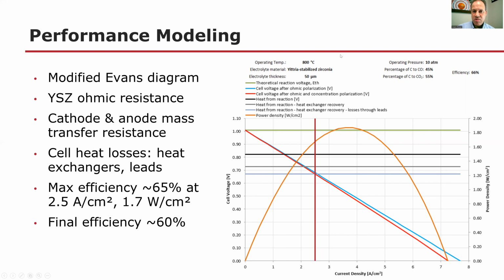So this is at 800 Celsius with a 50 micron electrolyte thickness. This is much higher efficiency, and we also have a much simpler flow sheet than these other gasification flow sheets, with just formation of the biochar, feeding in, air in, CO2 out. Very simple system.